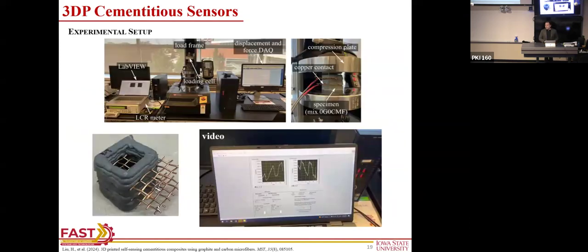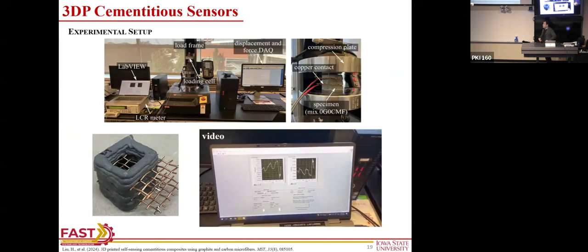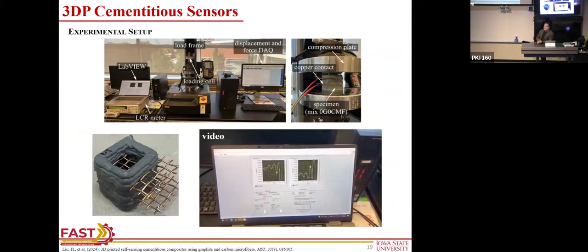Typical test that you will do if you try to make sensors on the concrete, you just press on it, actually. And you take measurements, you have a video with how it's done, we just apply different quasi-static loads on it, sometimes dynamic to look at dynamic performance. And we look on the left at the applied load, on the right is the measured resistance. You can see that it follows the load, and that's fantastic. So we look at these data and try to establish which one's the most sensitive to strain, and that will give us our percolation.